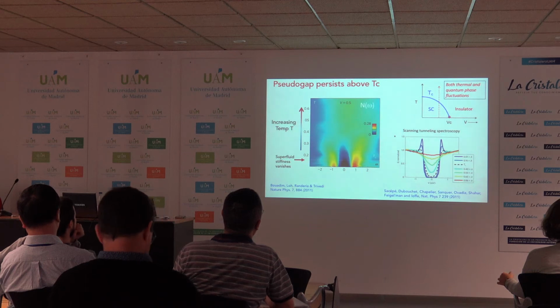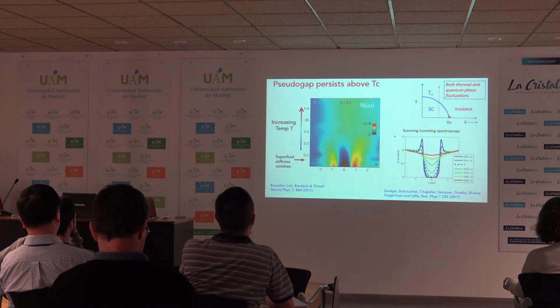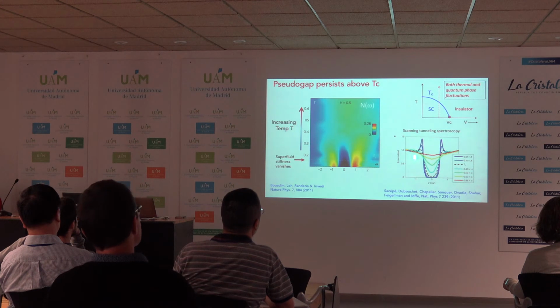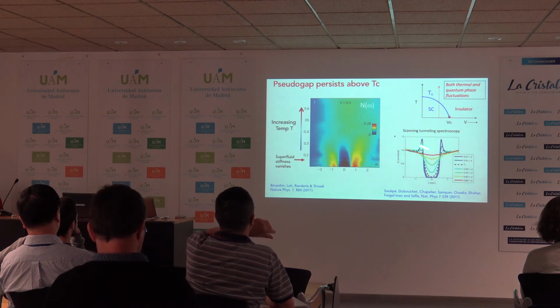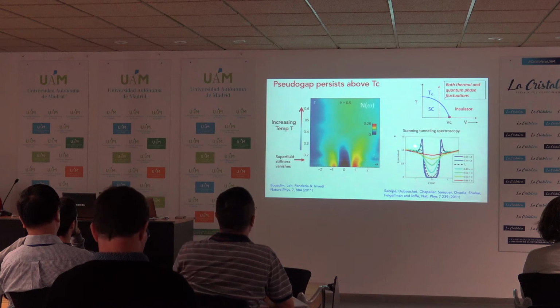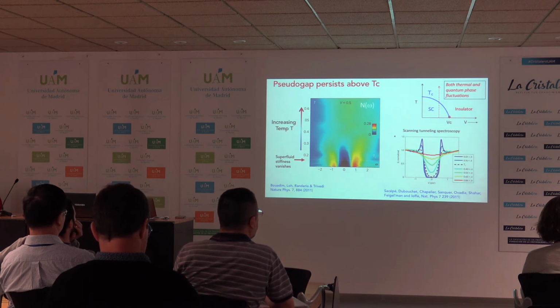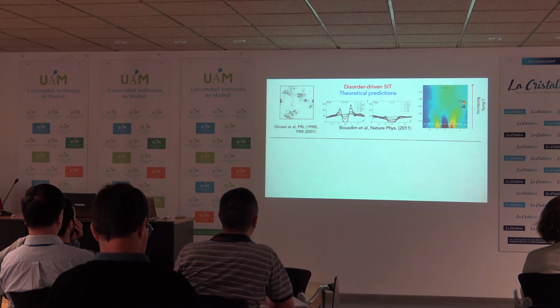This is some scanning tunneling spectroscopy data on this sample here, indium oxide, and what they have done is sitting on one of these superconducting blobs, they have taken the data at different temperatures. The dotted line is Tc, the transition temperature. Below that you see these sharp coherence peaks, but even above that, the pseudogap is persisting at finite temperatures. So that's a very nice corroboration of our results.